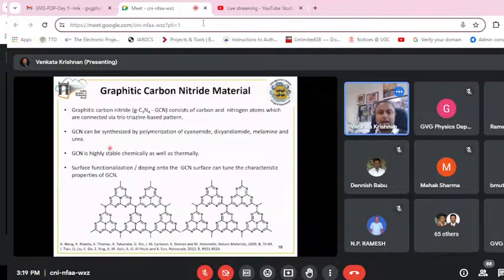This material, graphitic carbon nitride, can be easily synthesized by polymerization reaction of cyanamide, dicyandiamide, melamine, or urea—any of these can be used as a precursor. By using a very simple polymerization reaction, we can prepare this material, graphitic carbon nitride. And the prepared graphitic carbon nitride is stable both chemically as well as thermally.